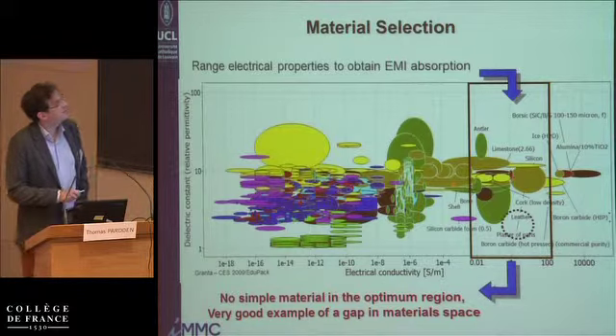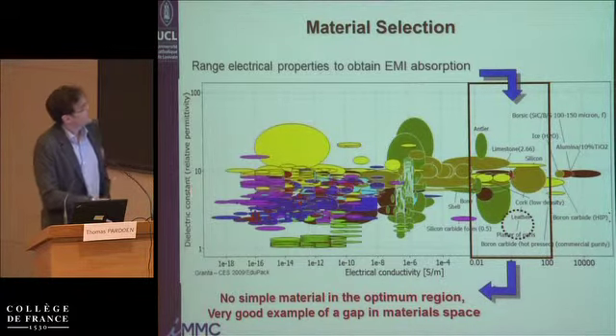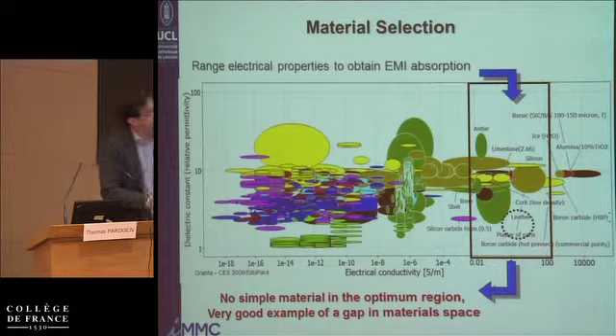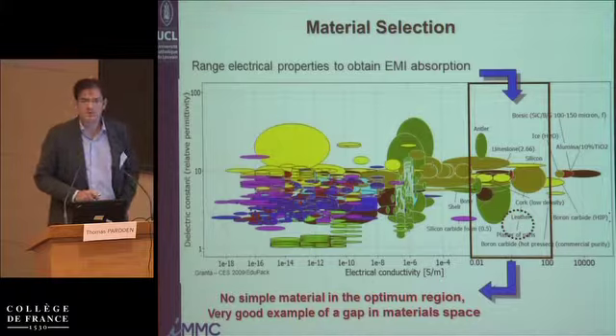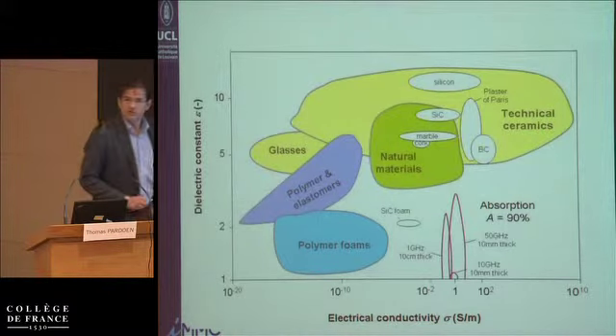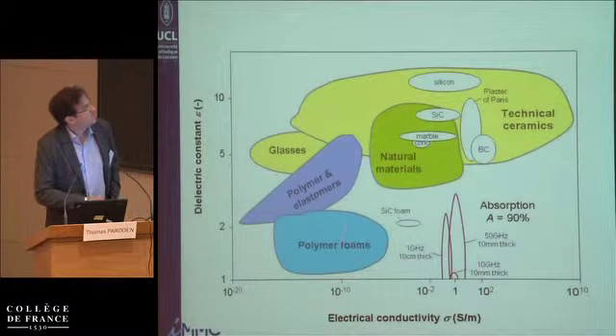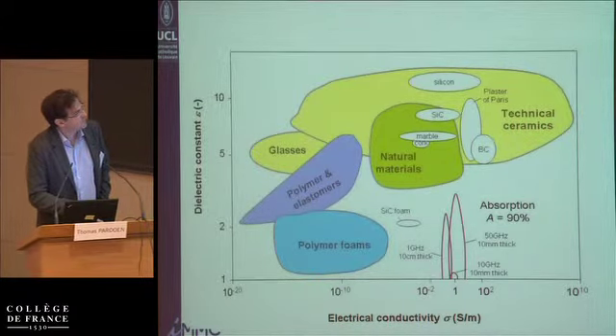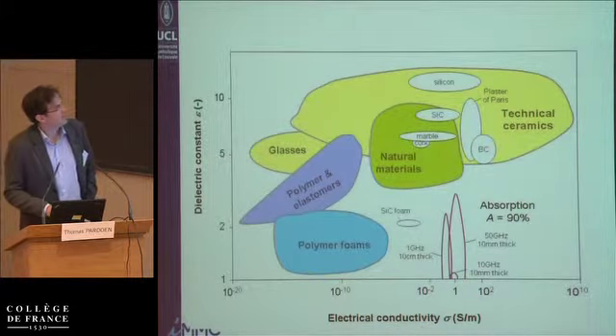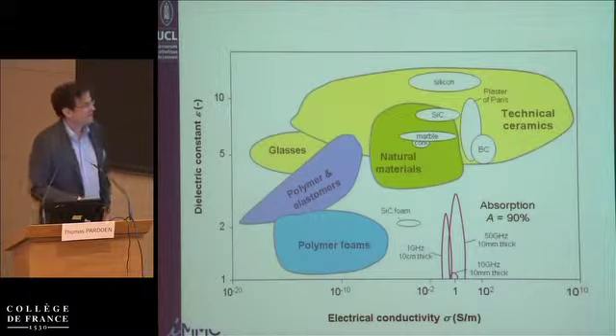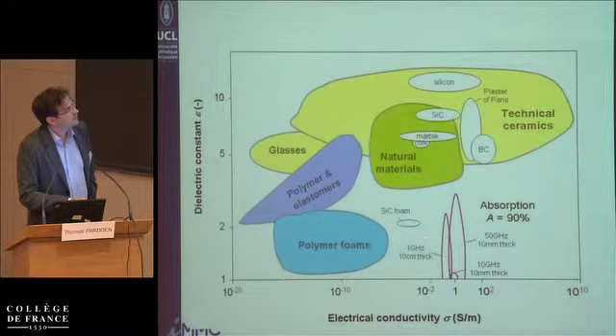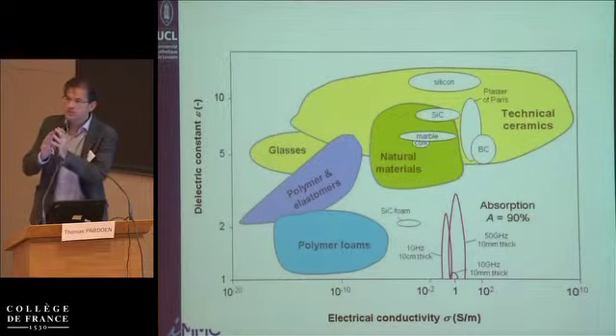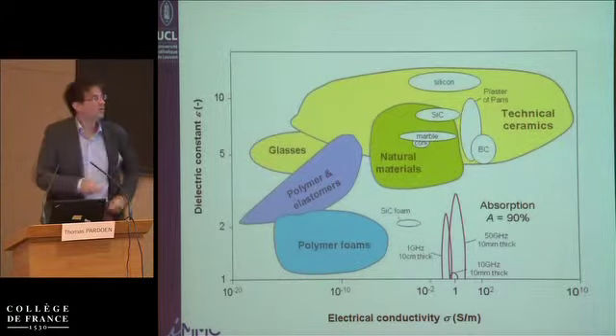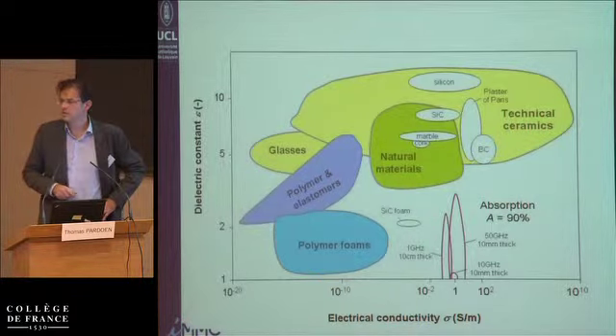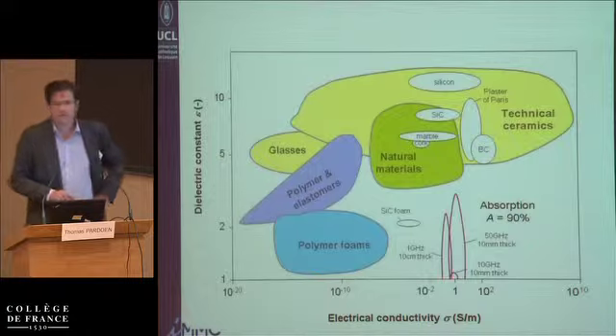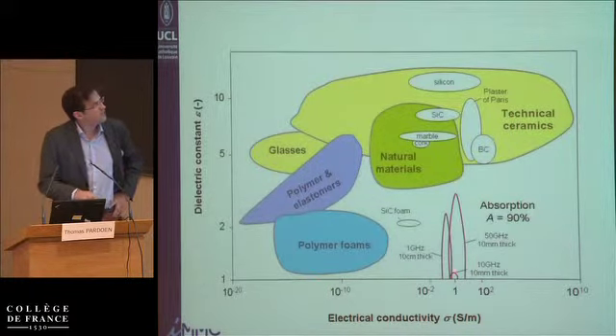We use EduPack here, and we plot all materials, dielectric constant as a function of electrical conductivity, and this is the area where we look for an optimum value. I've made a more simple schematic plot here, and you see the different families of materials, and you see the range of optimum absorption here. And this is the gap, where you see there are no materials here. There are a few materials that are not too far, but the region in which you can get high absorption is so narrow that all the materials around basically have zero absorption capacity. So you really need to have a very good control of the electrical conductivity here to reach this area.